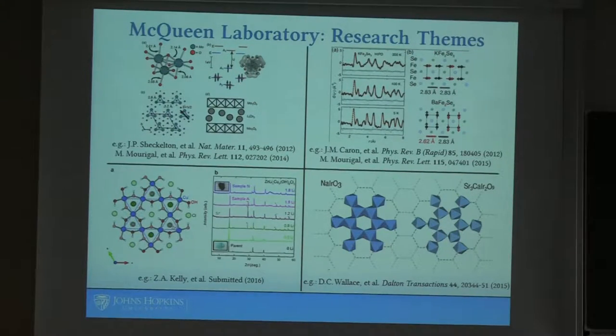Here's an interesting one - these are KFe2Se3 and BaFe2Se3. These are one-dimensional analogs of the iron superconductors. What do you gain by reducing the dimensionality? Well, you get rid of some of the degrees of freedom, and it lets you actually study some of the underlying physics without having to worry about them going superconducting. In fact, these things stay insulating the whole time, because they really are like two-by-infinity slices out of the iron-chalcogenide lattice.